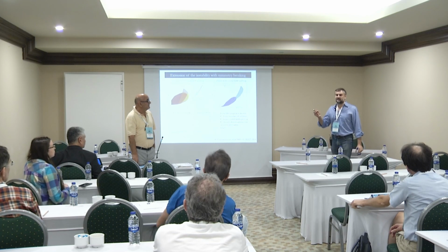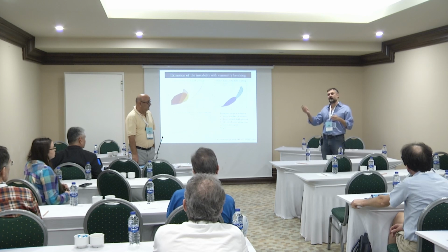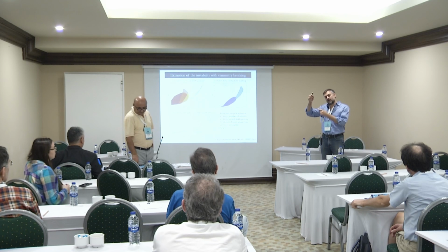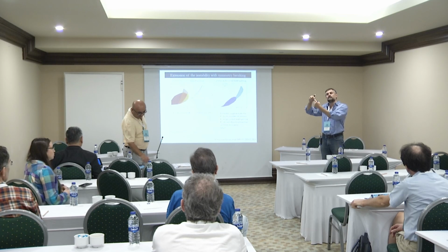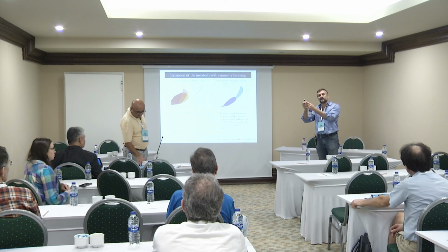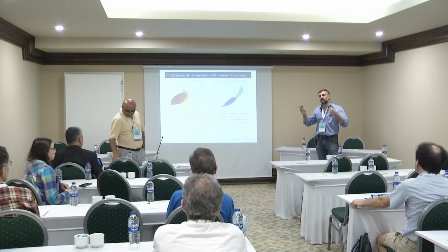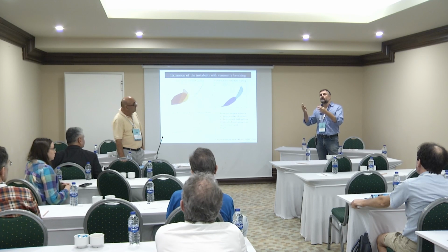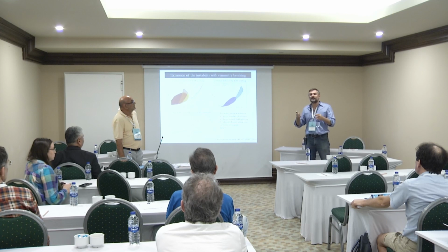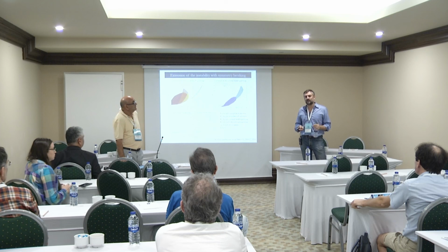So physically it is the density. That's because we have diverging compressibility and the two spinodals merge in this quantum critical point. So it's really the electronic density. And associated to that, there is the fact that the two metallic phases have a huge difference in quasi-particle weight. So there are some associated fluctuations of metallic character, if you want, if you're able to define that locally somehow. Okay, so it's between a very good metal and a very bad metal. I haven't fully explored that.